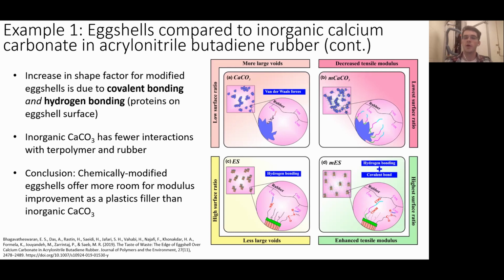And again, for the unmodified eggshells, they've drawn a diagram down here on the left. They're just stating that the proteins on the eggshell surface interacted with the nitrile groups on the rubber, which is why, without that covalent bonding, they saw a lower tensile modulus for the untreated eggshells rather than the modified eggshells. So the conclusion from this paper is that eggshells offer more room for modulus improvement as a plastics filler than inorganic calcium carbonate.